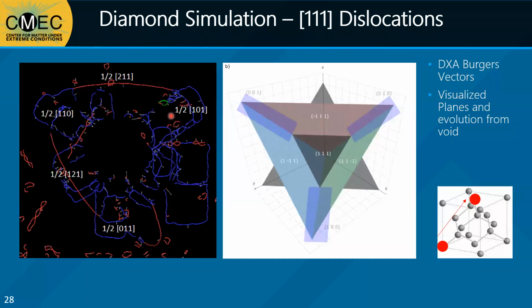These typically have a Burgers vector of 1/6 211. However, our dislocations here are 1/2 211, which is equivalent to going from the bottom corner of a diamond cubic system to the top face center. Because of the large distance that this dislocation covers, we call it a super dislocation.